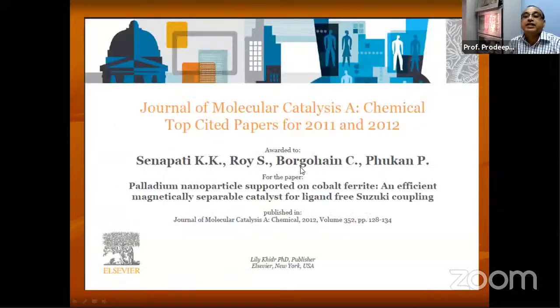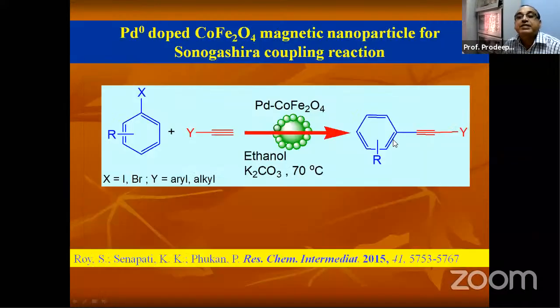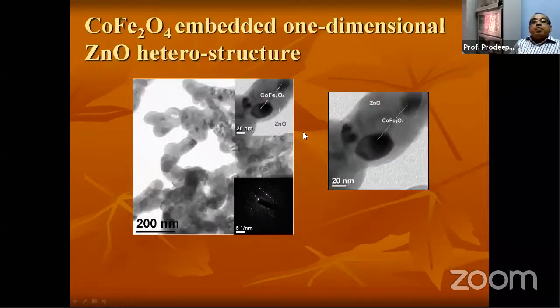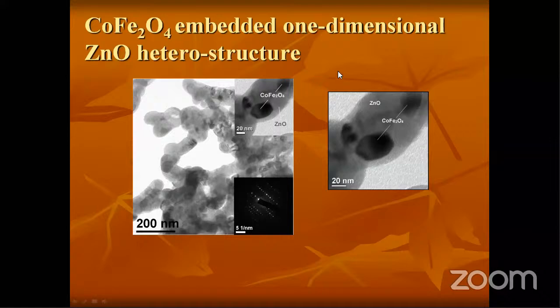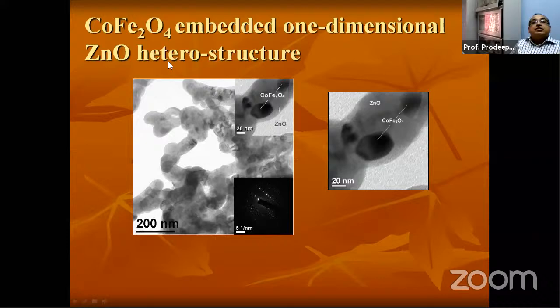And this also again became a very highly cited paper during 2011 and 2012. And next, Pd cobalt ferrite, we have done Sonogashira reaction also later, with the same compound. And this is the opposite thing we have done. What we did, cobalt ferrite embedded one-dimensional zinc oxide heterostructure. We have synthesized cobalt ferrite nanoparticles in presence of zinc oxide heterostructure.